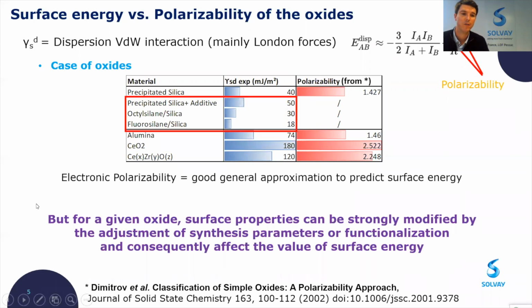But sometimes, here, for instance, in the case of silica, when we try to adjust the synthesis parameters or try to functionalize the silica, the surface energy can be very affected, as you can see here in this value.